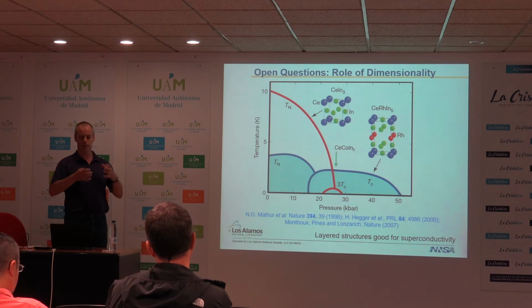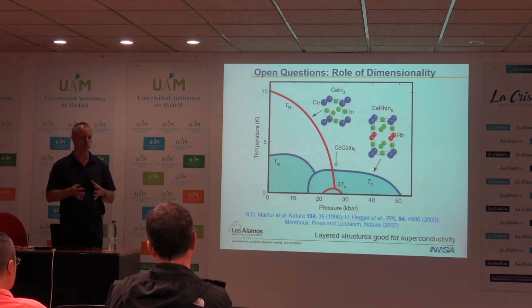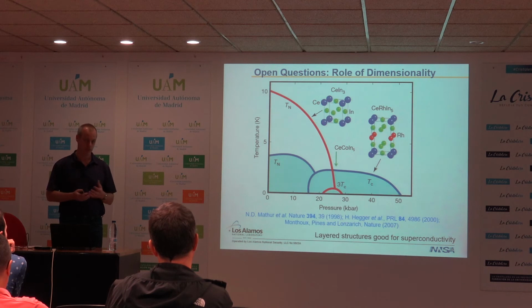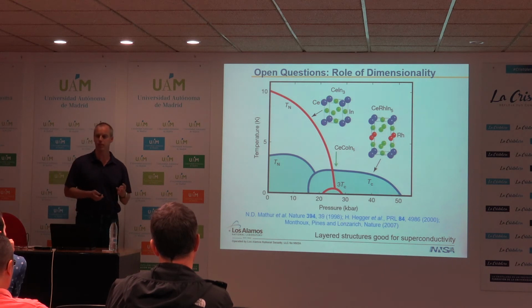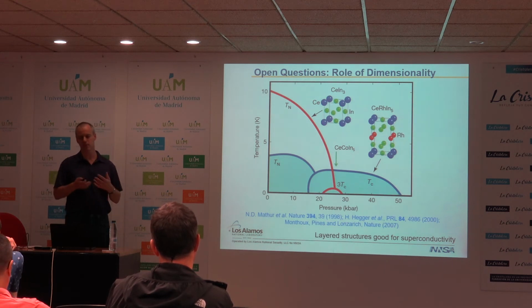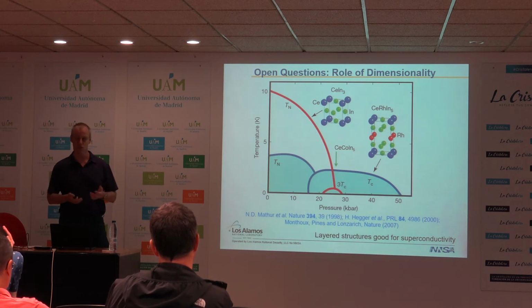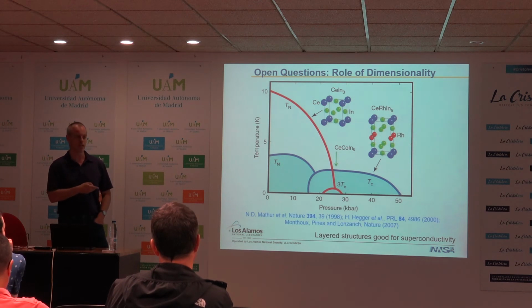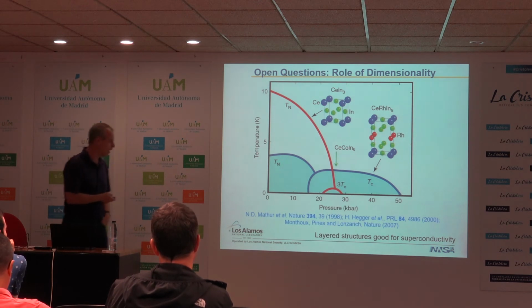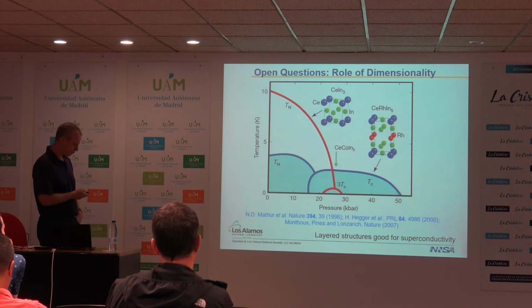So the Fermi surface of this material has nice cylindrical parts, so it does look 2D, but it also has very 3D pockets. So in fact, the transport anisotropy is only a factor of 2. The magnetic susceptibility, so whether you have Heisenberg-like spins or Ising-like spins, is also only a factor of 2. So it is still an open question as to how this reduced dimensionality really boosts superconductivity, specifically in this compound.